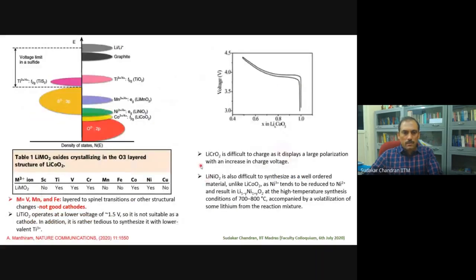Of course, a systematic study was carried out in his group. LiMO2 with a layer structure, and there were very few compounds they could see. For example, titanium was there, but the titanium had very low voltage for the reason that the titanium energy levels lie much closer to the lithium redox energies. On the other hand, vanadium, manganese and iron, which could be prepared in the layer compound, always either structurally transformed to spinel structure, or did not form good cathodes. Chromium compounds had very large polarization.